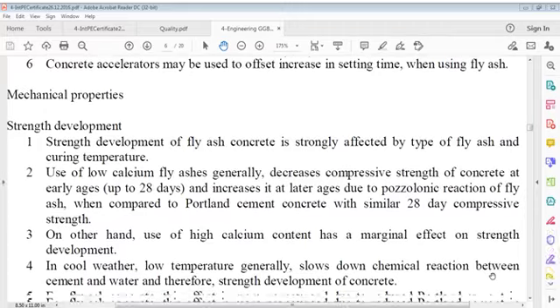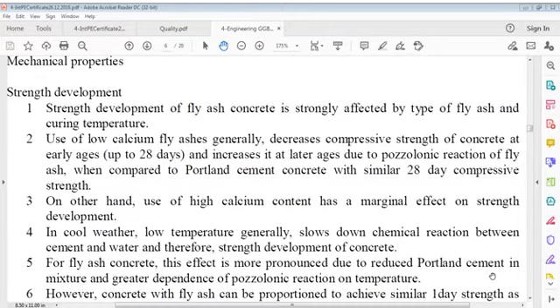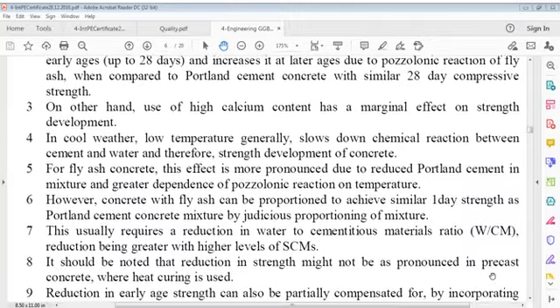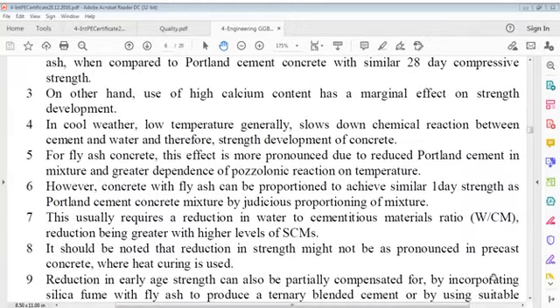Now mechanical properties. Strength development. Strength development of fly ash concrete is strongly affected by type of fly ash and curing temperature. Use of low calcium fly ashes: low calcium fly ashes generally decrease compressive strength of concrete at early ages up to 28 days and increase it at later ages due to pozzolanic reaction of fly ash, when compared to Portland cement concrete with similar 28 days compressive strength. On the other hand, use of high calcium content fly ash has a marginal effect on strength development.